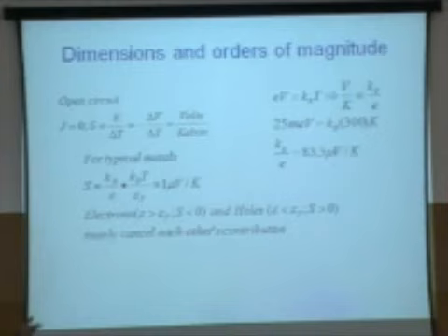One way to think about it is this: I have a metal at zero temperature, I have basically no excitation, so nothing happens. I heat it up, and I excite some electrons from below the Fermi surface to above. I call those electrons. Those which are below, I call holes. They both carry energy, but they have effectively opposite charge. So they cancel each other out, and that gives almost zero. So in many metals, if the number of electrons and holes are identical, then you don't get any thermopower. So the game is to make them as unbalanced as possible.